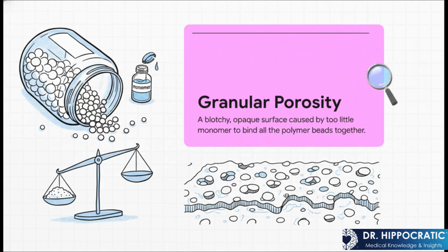If your ratio is off, say too much powder, or you forget to cover the mixing jar and some of that monomer liquid evaporates, you get this, granular porosity. What's happening is there just isn't enough of that liquid glue to fully coat and bind all the powder beads together, leaving these tiny gaps. The result? A weak, porous structure that looks all blotchy and kind of opaque.